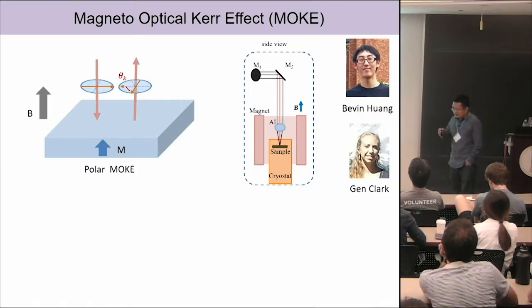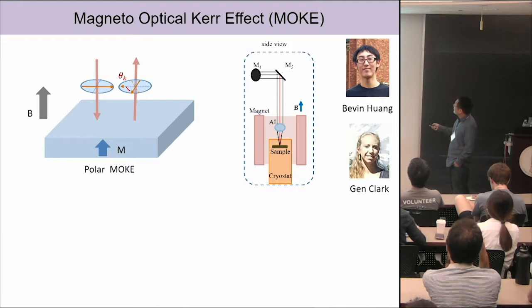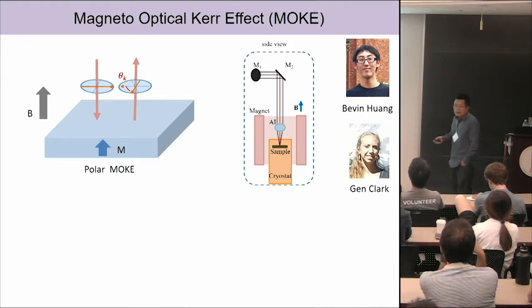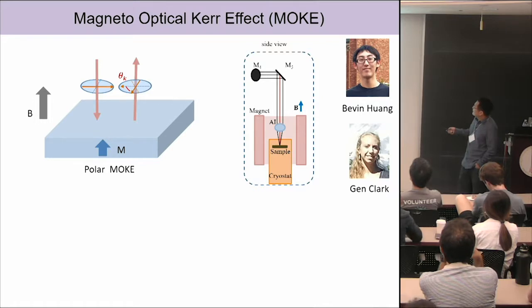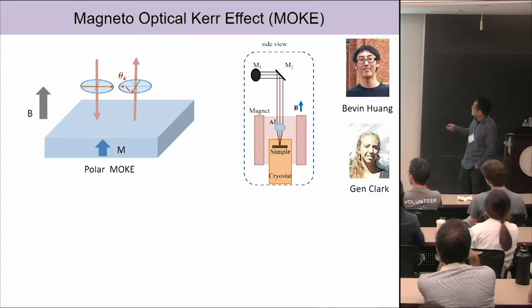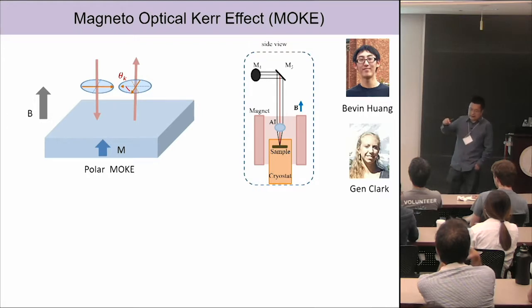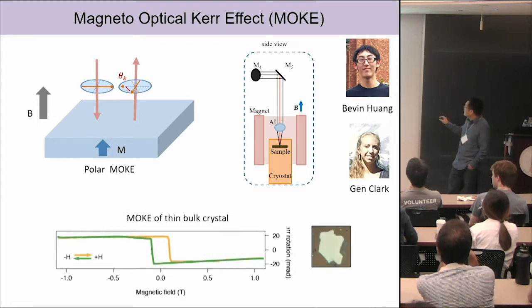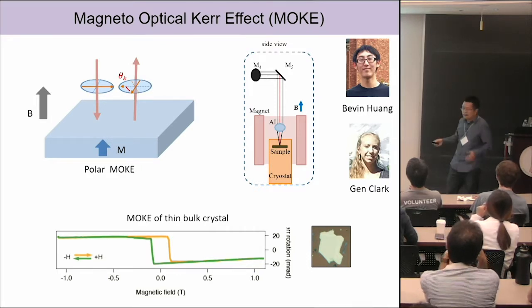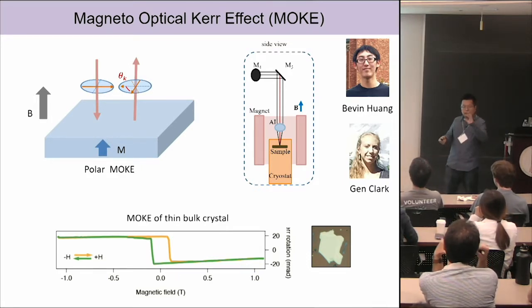So we started on these, like I said. We exfoliated, and we built these magneto-optical Kerr rotation measurements. It's quite a simple technique. The essence is you shine linearly polarized light onto the sample, and you look at the polarization rotation in the reflected light. This angle is called the Kerr rotation angle. The Kerr rotation angle is kind of a hallmark of time reversal symmetry breaking in the system. Well, the subtlety is that if you just see a rotation of the light, it doesn't mean you have a Kerr rotation, okay? Because there could be artifacts in the system that give you a little bit of rotation of the angle.